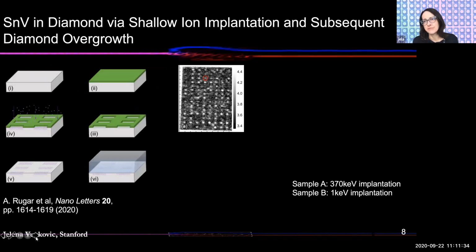As I mentioned at the very early slide, you have to deal with a variety of non-traditional fabrication methods because everything is much smaller than for superconducting systems, because you are operating at optical frequencies and everything pretty much scales down with the wavelength. And you also have to controllably insert these quantum emitters inside of the semiconductor lattice. So what we're doing is we're developing a variety of techniques that enable us to insert them at precise positions inside of the diamond, in this case, in a regular grid and with high yield.